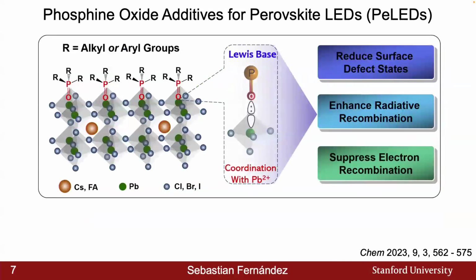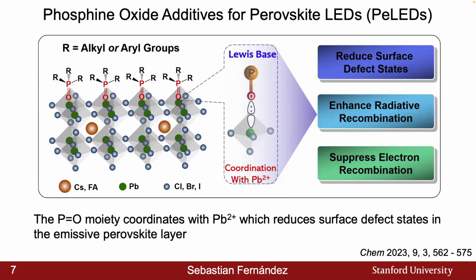And so recently there's been a new additive class known as phosphine oxide additives, in which what I want you to focus on here is that the phosphine oxide moiety can coordinate with the lead site within the perovskite, which in general can passivate and reduce the amount of surface defect states and enhance the radiative recombination within the perovskite thin film, really driving the emissivity of that thin film and hopefully leading to better performing devices. Additionally, it's also known within perovskite PV to suppress electron recombination, really showing the strength of this additive class, both within light emitting technologies and light absorbing technologies as well.